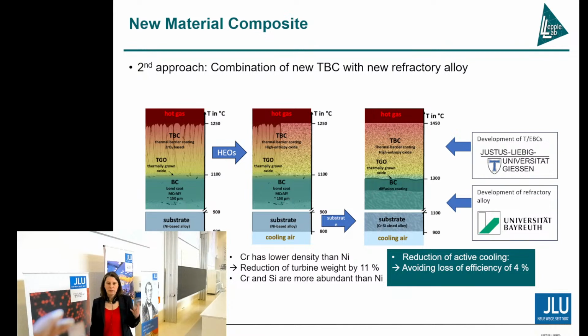So by implementing this new material composite, chromium alloy and high entropy oxide as TBC material, we can actually reduce the active cooling component because all materials can withstand higher temperatures, and thereby we can avoid the loss of efficiency which we usually have by this active cooling of approximately 4%.